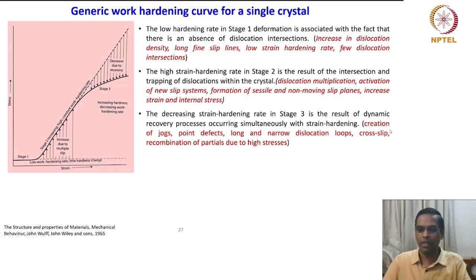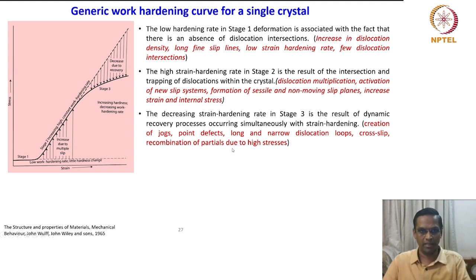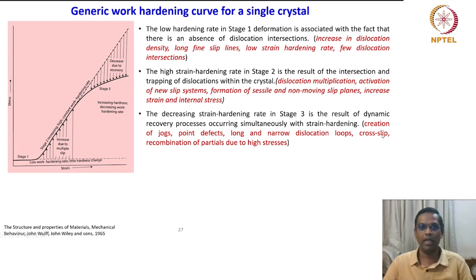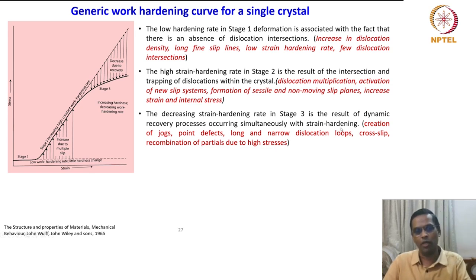The recovery process — including dislocation annihilation, dislocation loop formation, and rearrangement into lower energy configurations such as cells, dislocation walls, and sub-grain boundaries — collectively reduces the defect density and lowers the system's energy. When a positive and negative edge dislocation glide on the same plane in opposite directions, they form a perfect crystal — that is dislocation annihilation, and this reduces the total dislocation density as deformation proceeds.